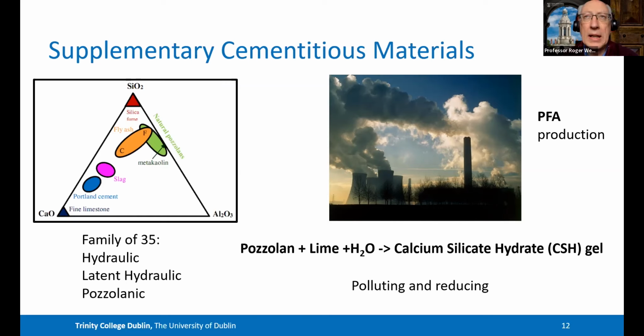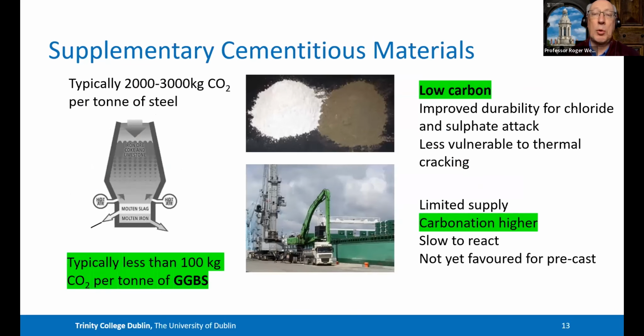But you do need the calcium hydroxide in order to get the pozzolans to react. So I'll be referring to that later. The one that is used in Ireland more and more now, very successfully used for particular applications, is slag, or ground granulated blast furnace slag. And we shouldn't forget that to create slag, you do need the waste product from the manufacture of steel. And steel, of course, itself has a very high carbon footprint, two to three times higher, at least, compared to cement. It doesn't come for free, but I think it's well recognized, and again, I don't want to argue over numbers, that slag is a low carbon cement, typically less than 100 kilograms of CO2 per ton. So while it's recognized as being low carbon, it has very particular properties.